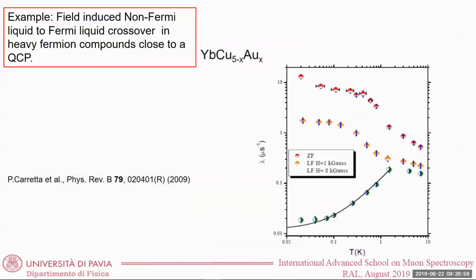Another example. I recall again this heavy fermion compound I have already shown in a past slide. And in this heavy fermion, if you are quite close to a quantum critical point, you can make the system switch from a non-Fermi liquid to a Fermi liquid behavior by applying a strong magnetic field. Well, not even strong, just a few kilogauss. And this is, for example, the case of this system. If we do zero field MUSR, we can see this divergent behavior of the longitudinal relaxation rate in zero field. But if we apply a magnetic field of a few kilogauss, we see a completely different behavior. And this is not easy to see because this is a double logarithmic scale, but this is a linear behavior plus a constant, which is the behavior that you expect for the relaxation rate in an ideal metal.